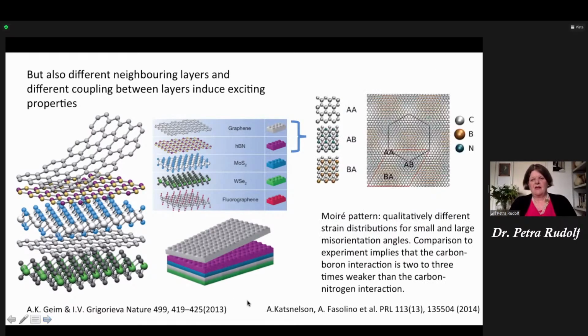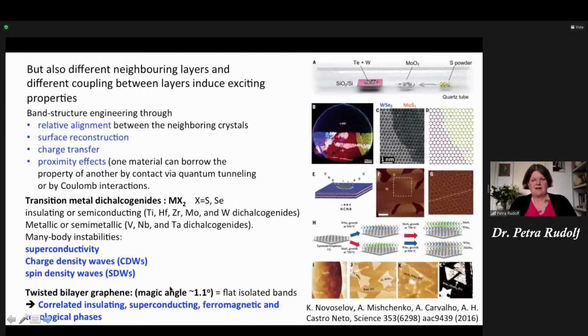And what is very exciting is that when you overlay these layers, you get the moiré patterns because you get a different strain between the layers also. And what one can see is that the interaction with the different atoms below is very different depending on the atom. So for example, if you put a layer of boron nitride and you put graphene on top, there is a different interaction between the boron and the graphene and the nitrogen and the graphene. And these things are studied a lot theoretically, but the first results are coming up. And we are also working on this right now.